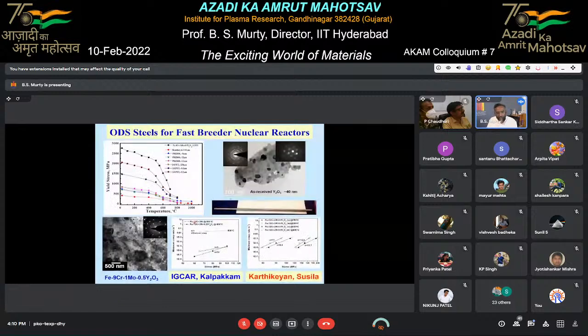We also did one work with IGCAR Kalpakkam, where we tried to make fast breeder reactor materials, called ODS steels, oxide dispersion strengthened steels, which are nothing but nuclear fuel pin tubes like this. This is all made out of powders. We made these ODS steel powders, and now, taking the help of IIT Hyderabad, DMRL, and NFC, they were able to make a 4-meter long tube with a diameter of around 6 millimeters. By simply hipping, then pilgering and extruding, people are able to make this kind of tubes.